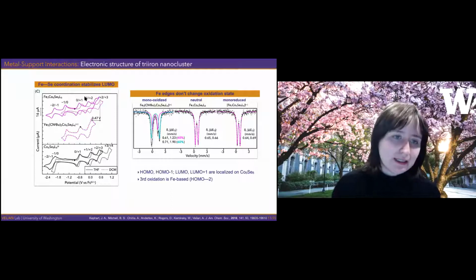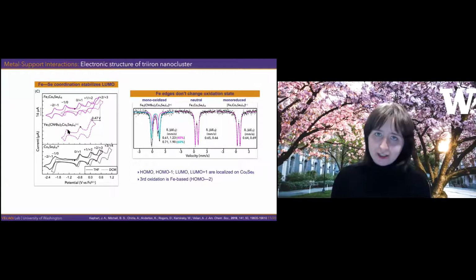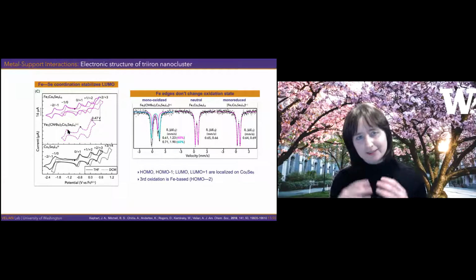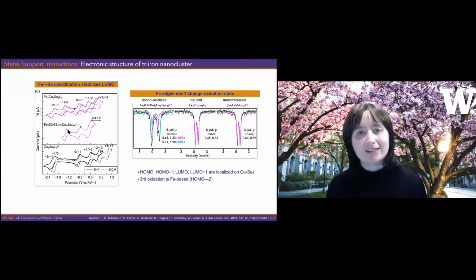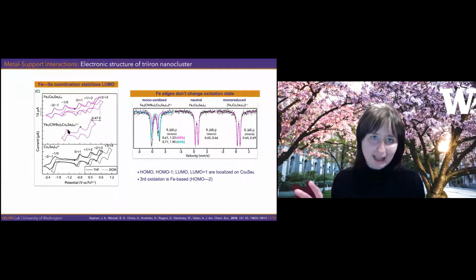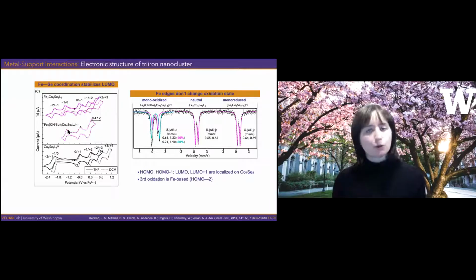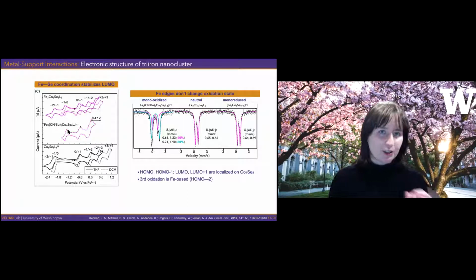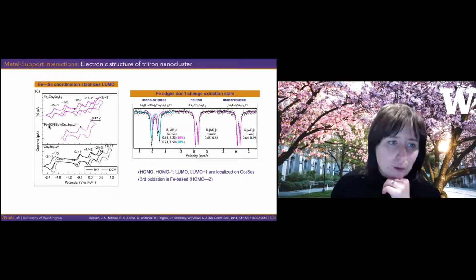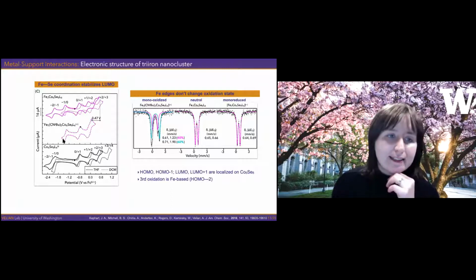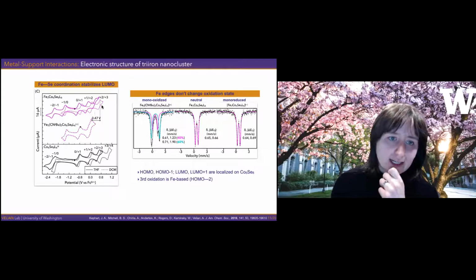The other thing that is happening that we can read from this electrochemical study is that if we change what ligands are bound to the surface, then we might be able to pinpoint where is the iron 2 to iron 3 oxidation. In its neutral state, we know for sure we start with iron 2. And the question is, at what point do you oxidize the iron 2 to iron 3? And can we see it? And so if we, for example, have an isocyanide coordinated to the surface, we should see, we thought, a difference between a case where we don't and the one that we do, and the oxidation event that is associated with that iron site should change the most.